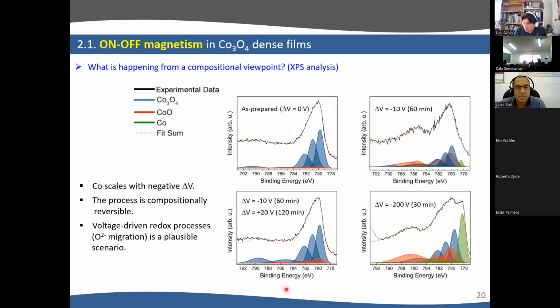We performed XPS analysis to try to understand what happens. And as you can see, first of all, the as-prepared sample, this is the experimental pattern, can be fitted just from peaks corresponding to Co3O4, with a little contribution from cobalt monoxide. After we apply minus 10 volt for 1 hour, you can see a broadening of this peak that can be fitted by adding an additional contribution here in green, and here the energy position corresponds to metallic cobalt. So this is an indication that we are indeed forming metallic cobalt.